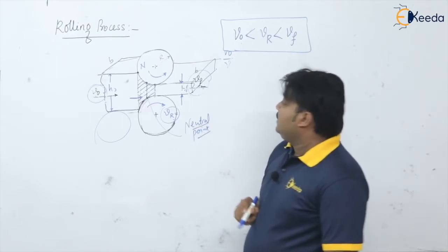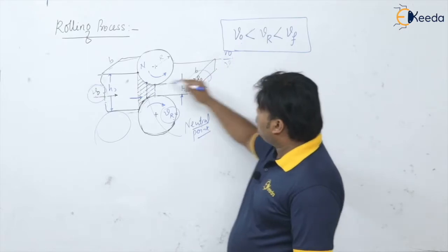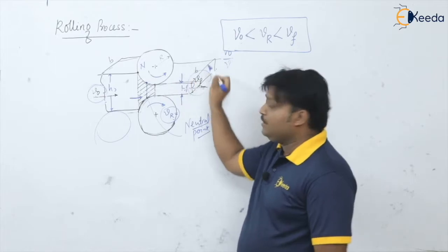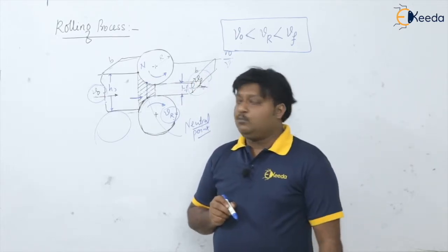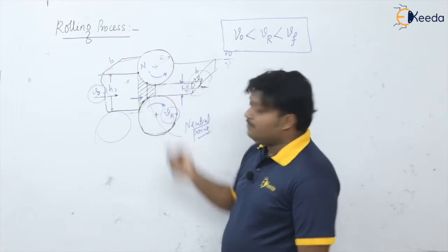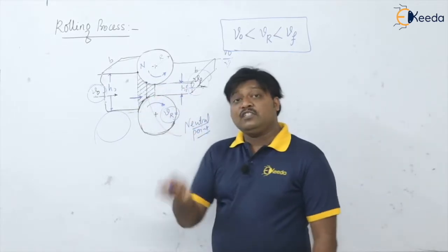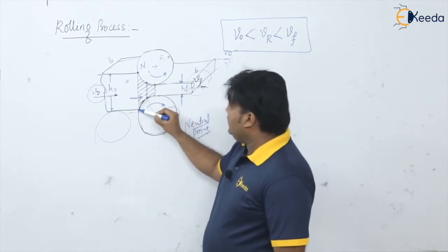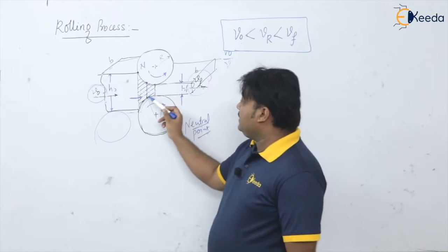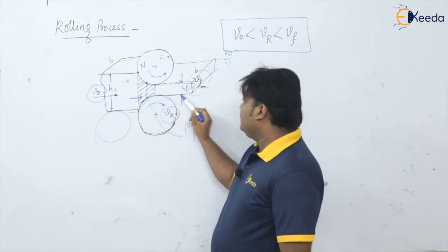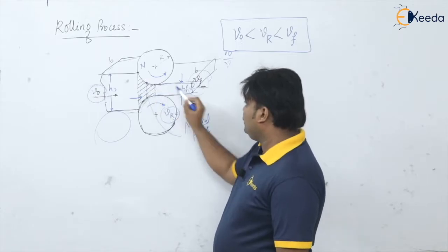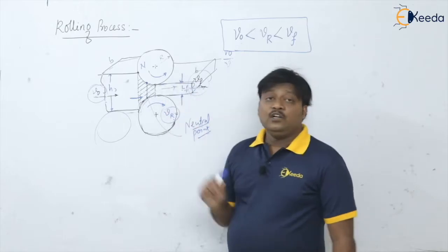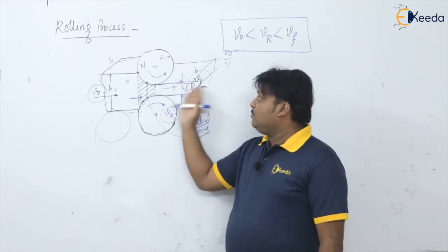Here also, at some moment in linear velocities, the linear velocity of the plate gets matched with the linear velocity of the roller. That point was the neutral point, where the relative velocity is zero. Now once the neutral point is passed by the strip, again what happened? As we know, because of the flow stresses, it is moving with a quite larger velocity than the roller, and it will reach the maximum at the end.